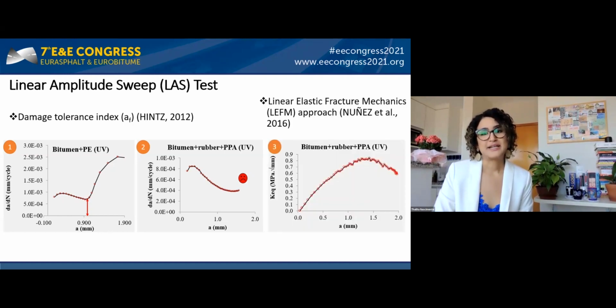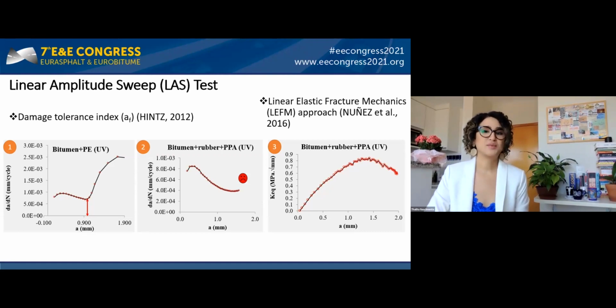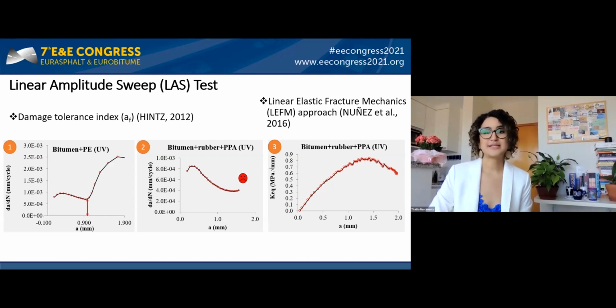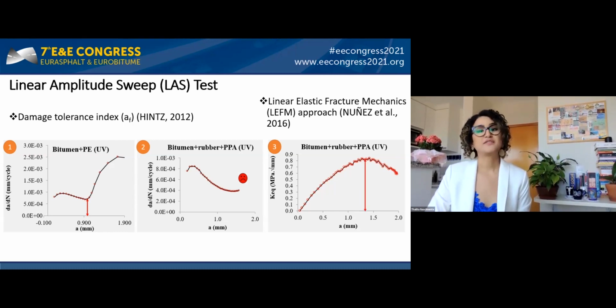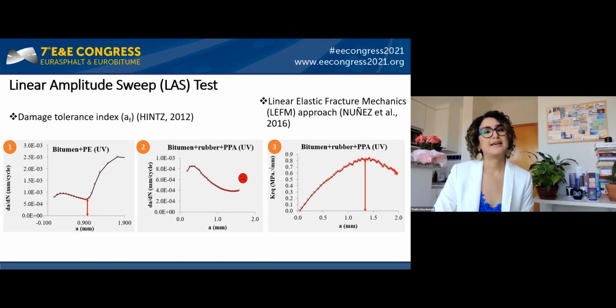So, as an alternative to this issue, we also use in this work the approach based on the linear elastic fracture mechanics, LEFM, proposed by Nuñez and others in 2016. This approach considers the macrocrack propagation in the material observed during the test. The failure criterion is the peak of the curve stress intensity factor K versus crack length a. Then, applying the LEFM approach, it was possible to obtain the crack length for materials such as the bitumen plus rubber plus PPA, as we can see in figure 3.